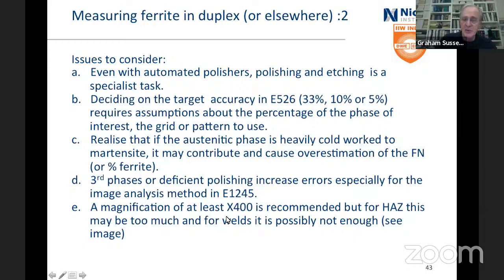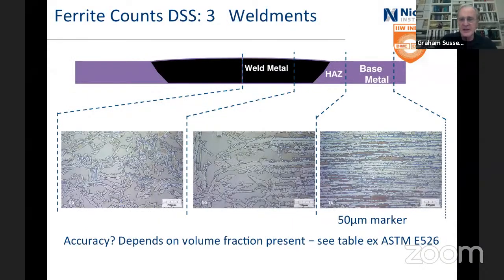Interestingly, the standard actually recommends that you use a magnification of at least 400, but that may mean that the heat affected zone is a bit too narrow to be able to use that, because you really can't go measuring the ferrite in heat affected zone and weld and parent material and expect that they'll all be the same, because they won't. And here's an example.